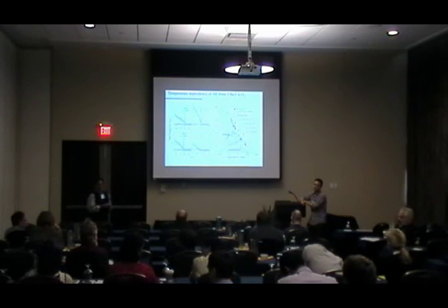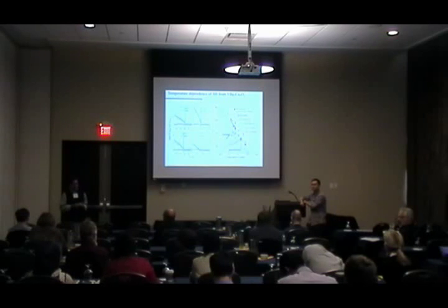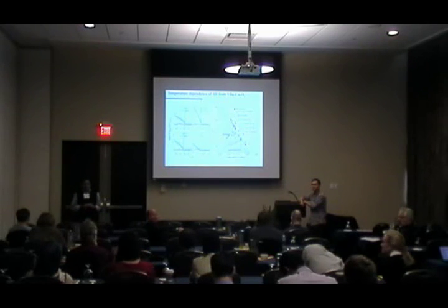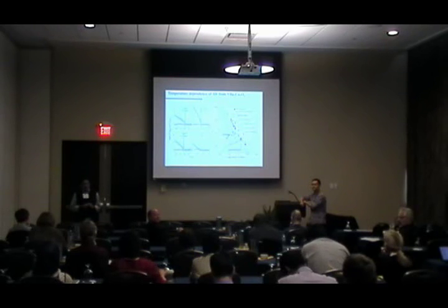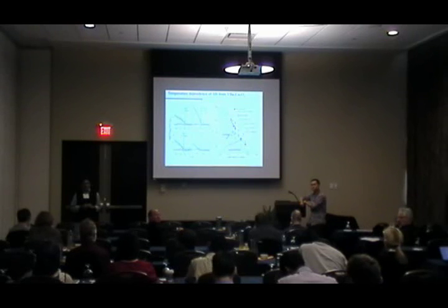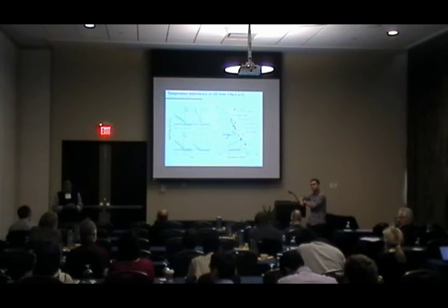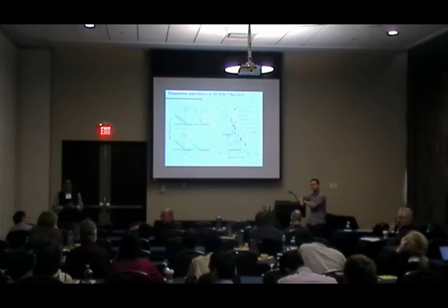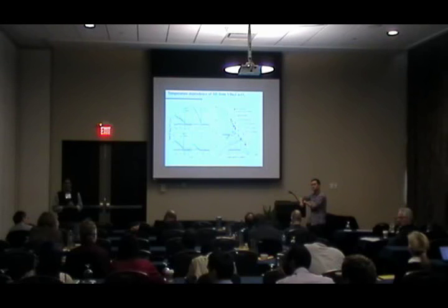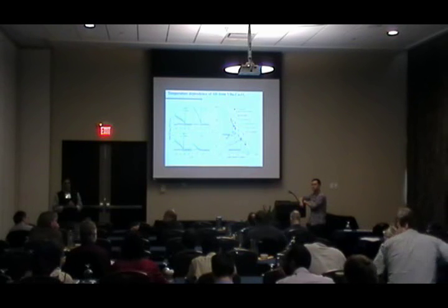If I may just follow up on this, in thermodynamics, you have the Clausius-Clapeyron equation for first order phase transitions. And there's a continuous transition analog, used to be known as the Pippard relations. There are many susceptibilities which are related to each other across a phase transition. And in the old days, if you wanted to call it a phase transition or not, what people used to do is look at these various susceptibilities, like the specific heat, thermal expansion coefficient, things of that sort. They're related to each other because they are thermodynamically mandated.